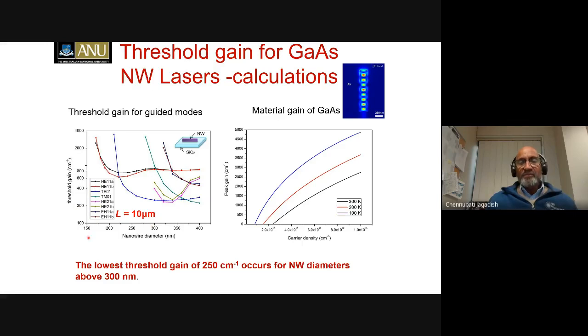In fact, I'm not plotting from 0 here. You can see that the smaller the diameter of the nanowires, the threshold gain for lasing is so high that you end up burning these nanowires, damaging these nanowires before you can get any lasing taking place. So that's why the design really plays an important role. Simulations play an important role.